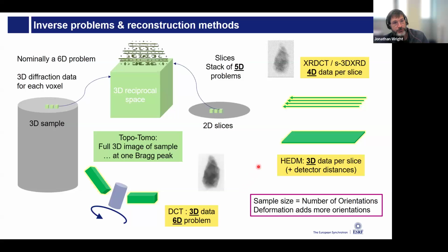As the sample becomes more deformed, then we try to make the beam smaller, so we can take slices. There's this kind of HEDM or 3D XRD method where you do 2D slices and try to reconstruct the grain maps. And what's growing a lot recently is this XRD-CT or scanning 3D XRD approach. So in this case, we scan a small beam across the sample and we do a rotation at each point. So we have this kind of 2D scan of position and rotation on the sample and a 2D diffraction image at each point. So we have this kind of 4D data set and we're reconstructing a 5D problem, which is this diffraction pattern at each point.